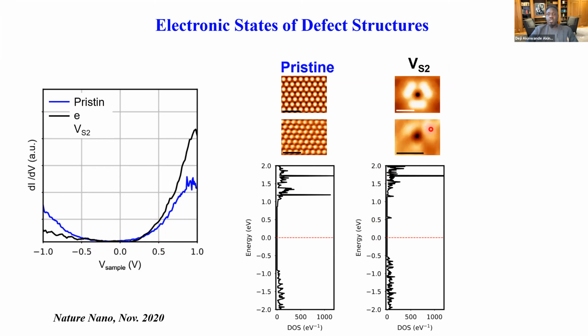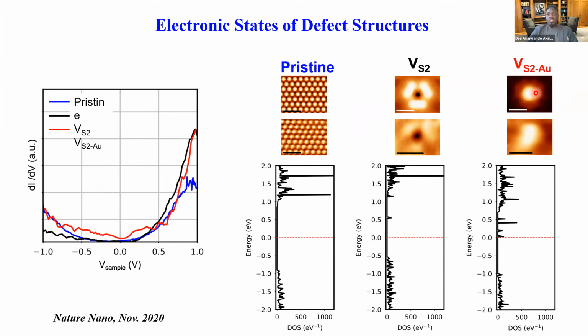We have simulated images and experimental images, but the metal atom adsorbed onto this vacancy does conduct. If you look at the spectroscopy, you can clearly see conducting density of states, and this correlates well with DFT calculations. So the bottom line in terms of the mechanism is you have a metal atom - in this case gold, but it could be a variety of metal ions - that can favorably adsorb onto the vacancy. They're very stable, but they can be debonded by reverse voltage subsequently, and this can repeat itself over and over again.